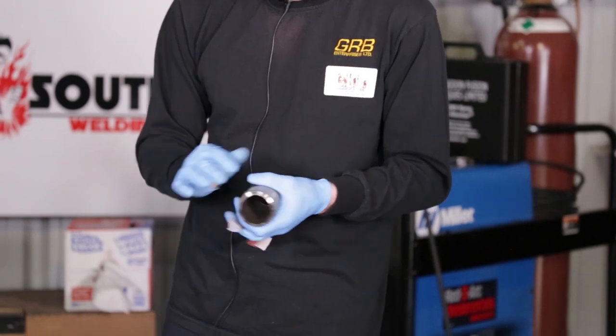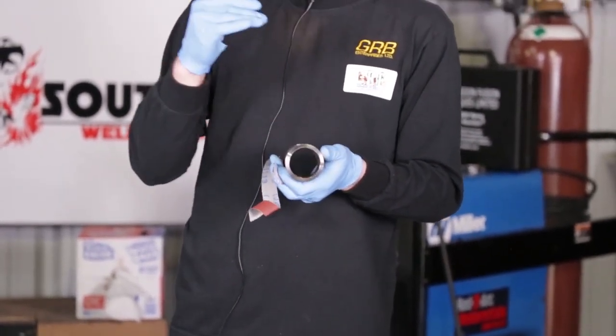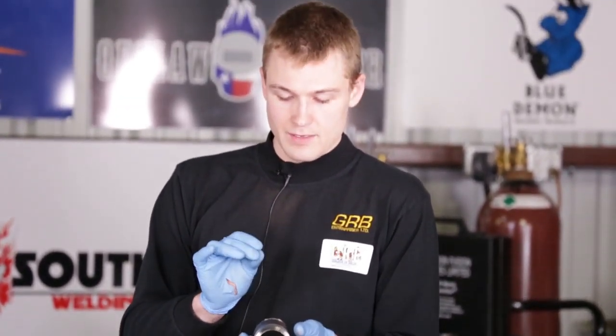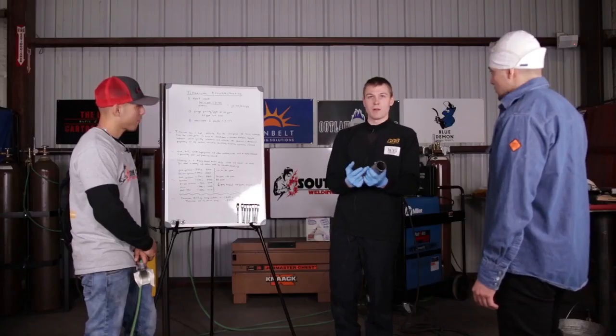Now the oxide melts at a higher temperature than the base material, but the thing that needs to be known about the oxide is that it contains oxygen. If I weld this and did not remove the oxide layer externally and internally and off the bevel, even if I had 10 parts per million on my TIG torch, 10 parts per million on my trailing shield, and 10 parts per million internally as a backing gas, I don't have enough oxygen to interact with the metal as the temperature elevates, so it's not going to oxidize. But because I did not remove the oxide layer, which contains oxygen, that oxygen is now going to interact with my weld puddle, and it's going to form oxides.